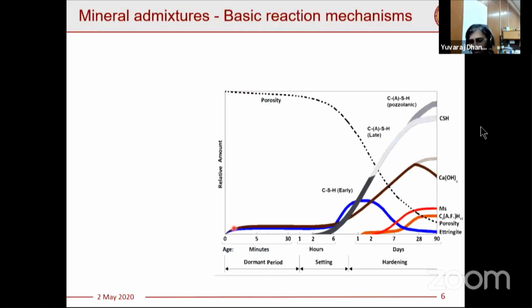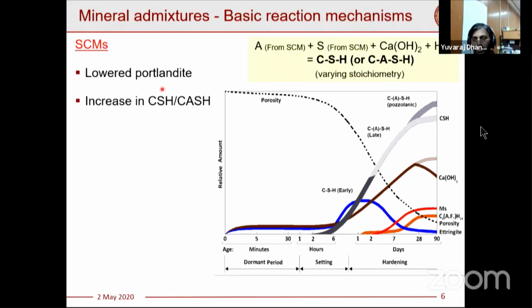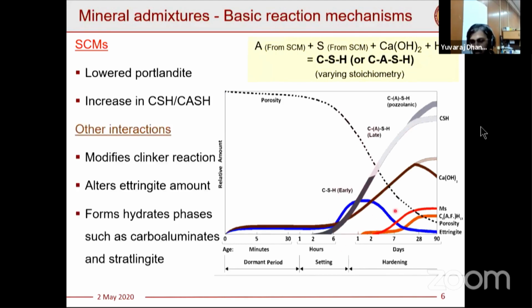Right? So trying to look at how the process happens over the period of time. This is a typical chart which you will see in textbooks, where initially you have formation of ettringite, CSH, and calcium hydroxide. And over the period of time, you start having a later reaction of pozzolans, this most talked about pozzolanic reaction, which leads to consumption of portlandite and increase in pozzolanic CSH. But what we also need to understand is there is a whole lot of impact which SCMs can bring about during the main hydration period itself.